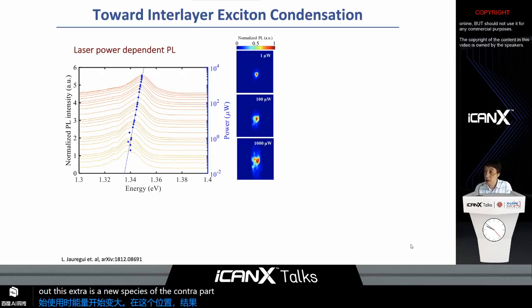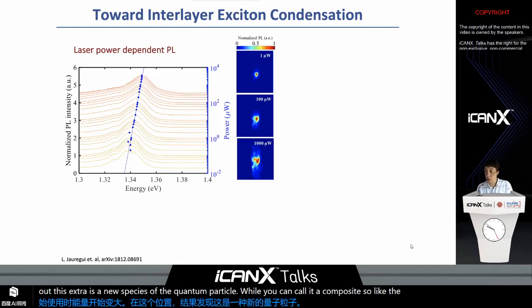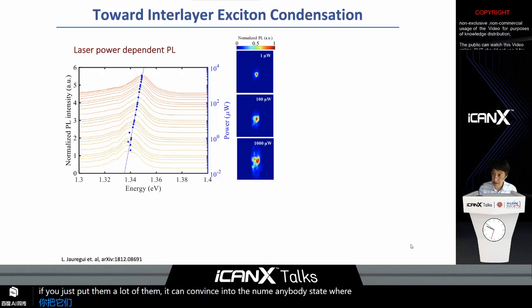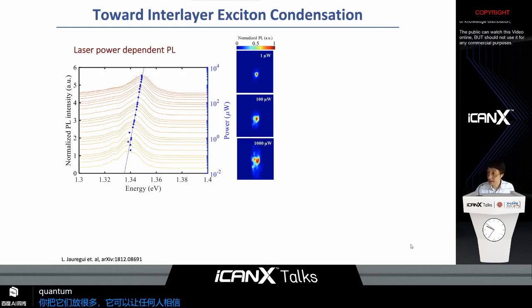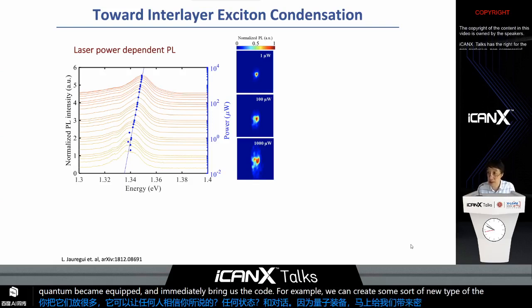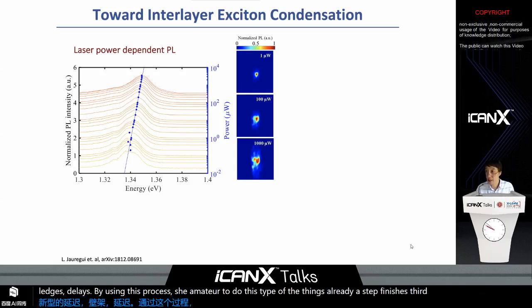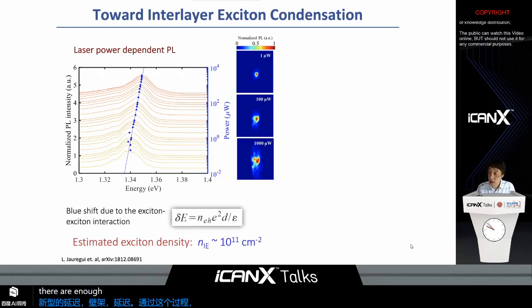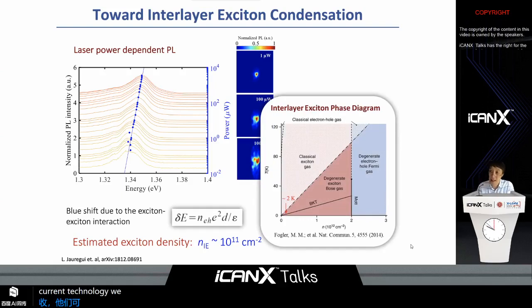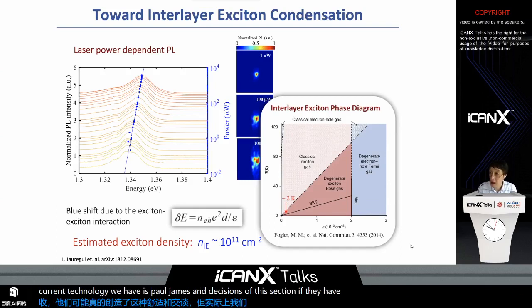It turns out this exciton is a new species of quantum particle, what we can call a composite boson. Like all bosonic quantum particles, if you put a lot of them together, they can condense into a new many-body state, what you call a Bose-Einstein condensate, and that becomes quantum mechanically coherent, right? This immediately suggests that we can create a new type of laser by using this Bose-Einstein condensation. Can we actually do this? The initial study we present here shows that there are enough excitons moving around that they may actually create these Bose-Einstein condensates. But with the current technology, these exciton Bose-Einstein condensates, if they happen, can happen only at low temperature. Can we create them at even higher temperature?